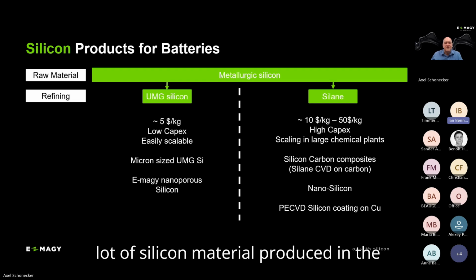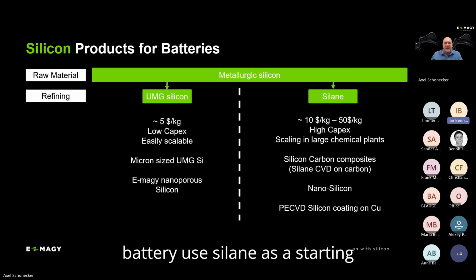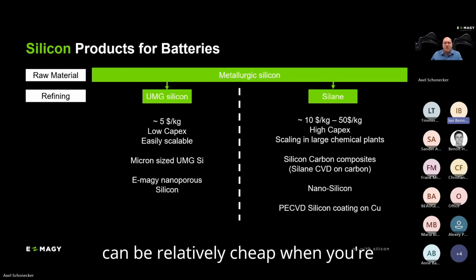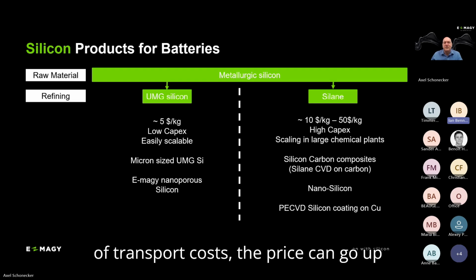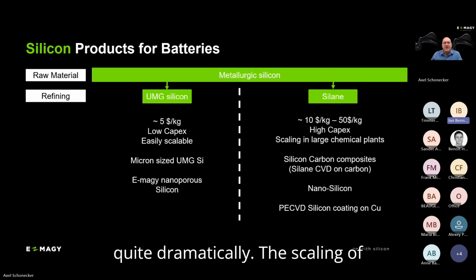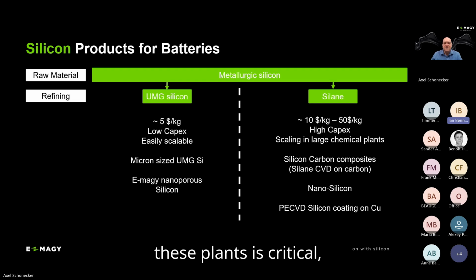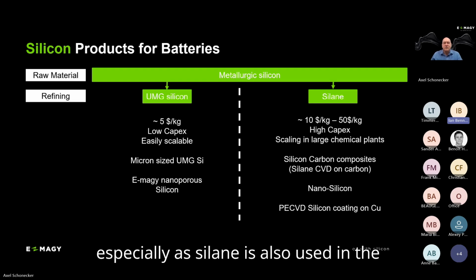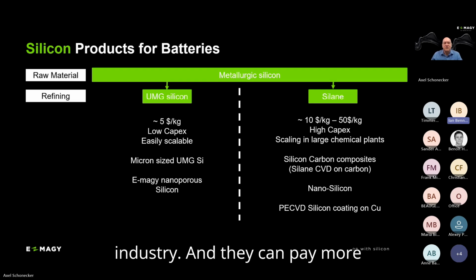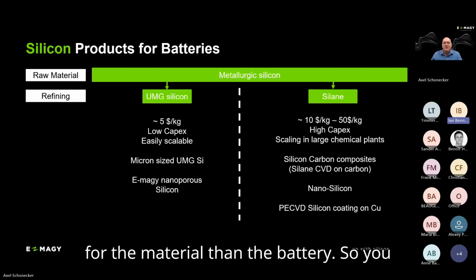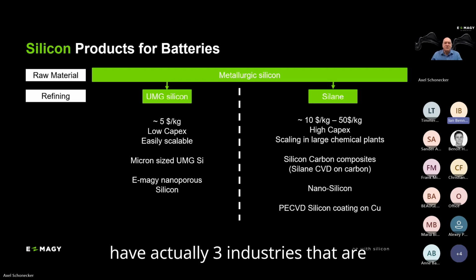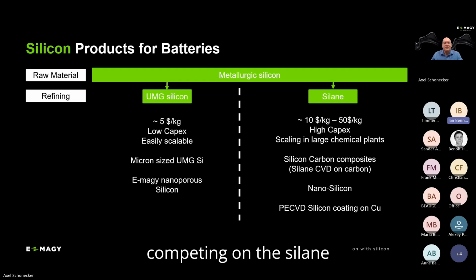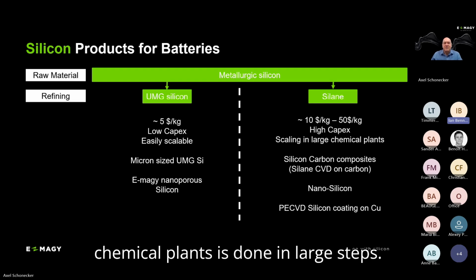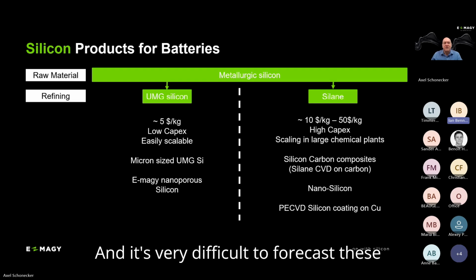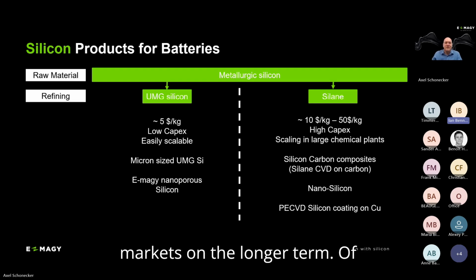A lot of silicon material produced for the battery uses silane as a starting material. As indicated, silane can be relatively cheap when you're close to a silane plant. If you add a lot of transport costs, the price can go up quite dramatically. The scaling of these plants is critical, especially as silane is also used in the photovoltaic and in the semiconductor industry, and they can pay more for the material than the battery. So you have actually three industries that are competing on the silane production, which means scaling in large chemical plants is done in large steps, and it's very difficult to forecast these markets on the longer term.